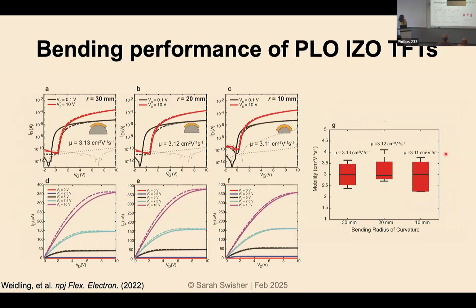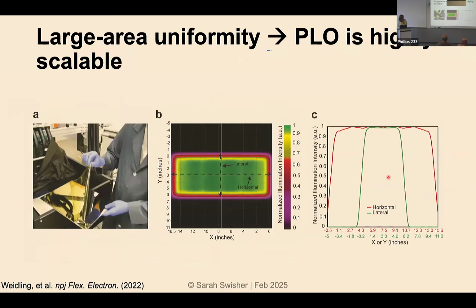And when we take that lifted off device and we bend it to various radius of curvature here, and we measure the transfer and output characteristics, again, the IZO TFTs, because of that amorphous structure, are very stable during that bending operation.